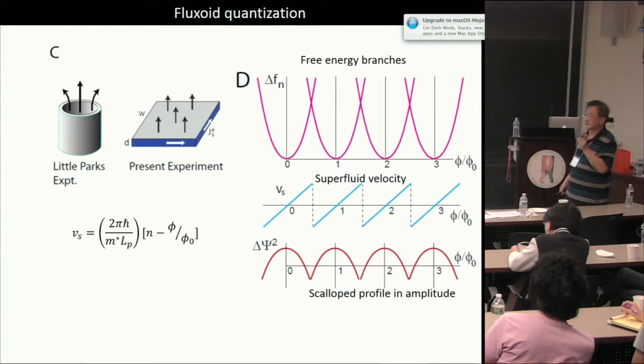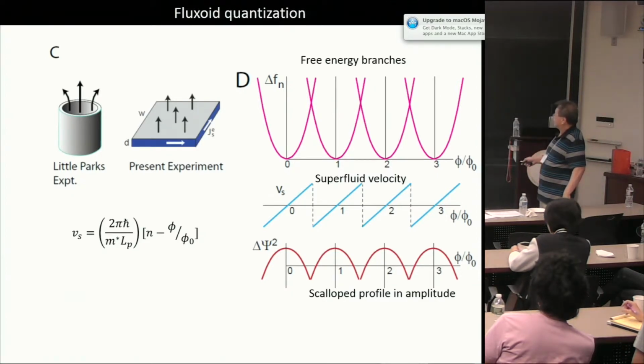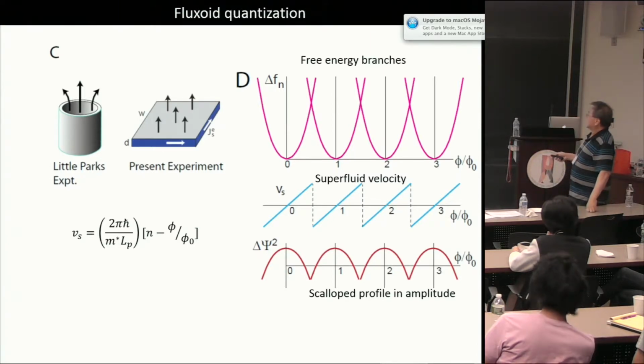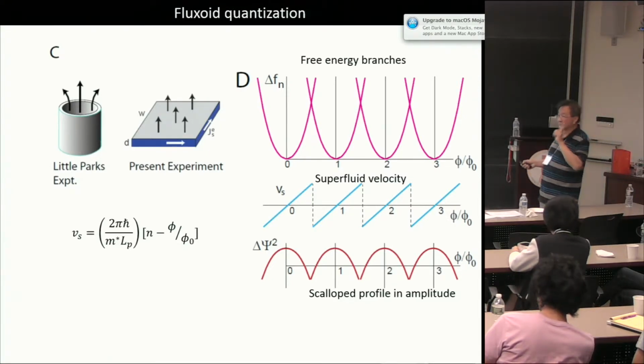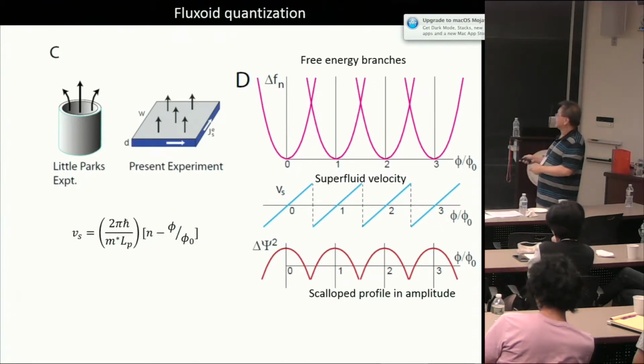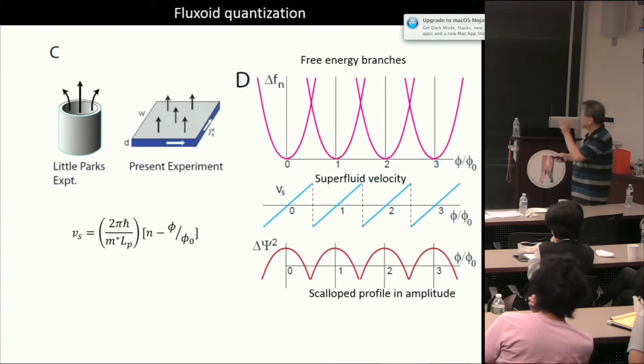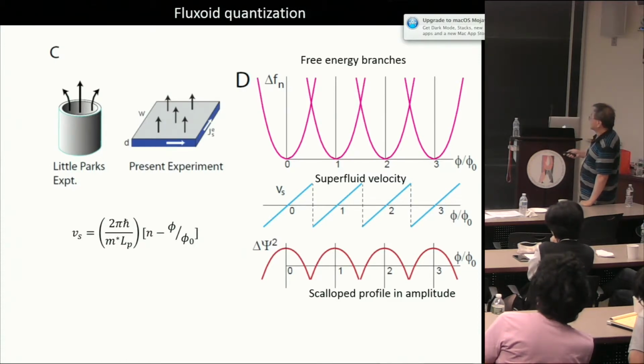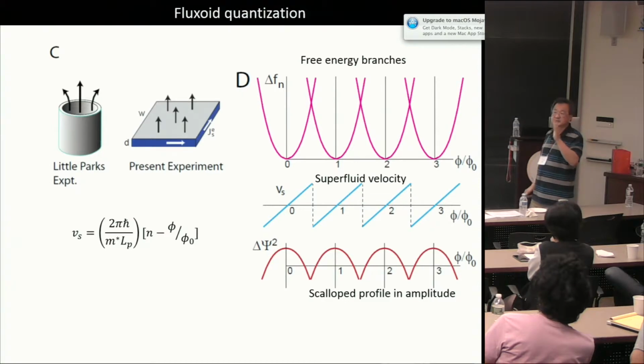And we think this is exactly what's happening here, except we are performing the experiment in a totally different regime, right? We are going to very low temperatures, 20 millikelvin, the TC is 100 millikelvin, right? So we are in the very low temperature limit where the order parameter is fully saturated. But now we are applying a large current to kill the order parameter. And then we're seeing this appear. All right, so this I hope will become more convincing in the next slide. So we are repeating the Little-Parks experiment, not using temperature to kill the order parameter, but using a critical current to kill it, and therefore we're seeing this at very low temperatures.